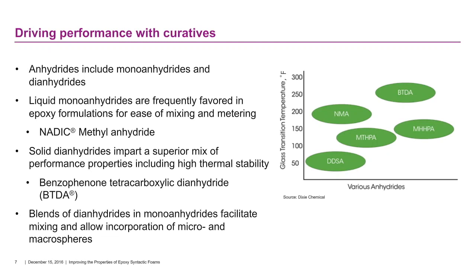The hindrance is that these are solids. So now you're trying to disperse a powdered material into this mix, and you can understand some of the hindrances and the aggravation involved in doing that. So if you can put blends together, this is where we see a benefit. And if you look at this quick little graph showing different levels of glass transition performance, you see that when you start looking at liquids and maybe incorporating with the dianhydride, you can really make a marked increase in Tg and drive some of those things that we've been speaking about: heat resistance, and overall performance of the syntactic foam in service.